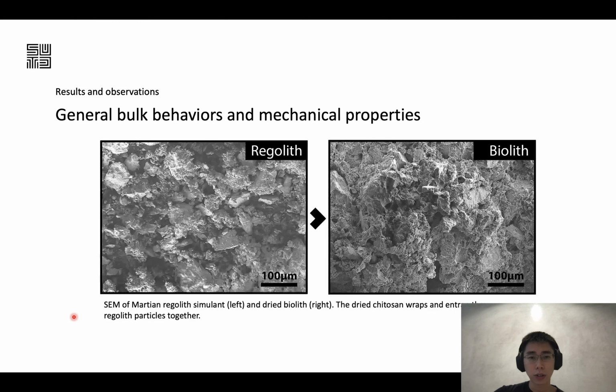Now, when it's dried, we took the samples and put them under scanning electron microscopy to observe what structures are being formed. What we observe is that in the dried samples, the chitosan crystallizes, it shrinks, and then pulls the particles together, seemingly entrapping them and physically agglomerating them together.